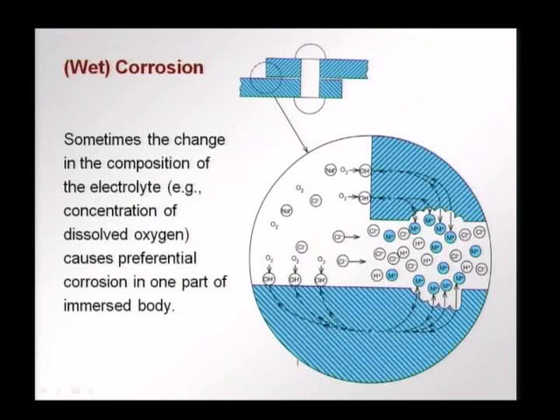The process of wet corrosion also can tell us how we can design materials or design components such that corrosion is prevented. We see that when the composition of an electrolyte changes, that is the concentration of dissolved oxygen changes in the electrolyte, this can cause preferential corrosion. The part that is getting less oxygen will corrode more or become anodic, say in this case of a riveted joint. If we have the joint such that water can go in and there is water stagnation in this area, obviously the part that is inside away from the surface will get less oxygen. So, this part becomes the anode and this starts losing material, metal starts dissolving from the interior in the anodic part and we have now a cell that is set up.